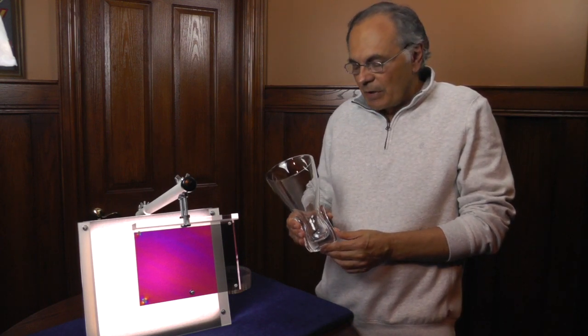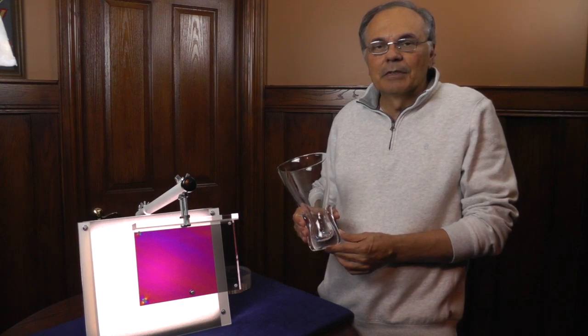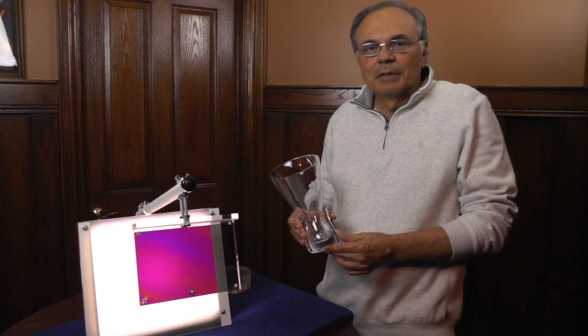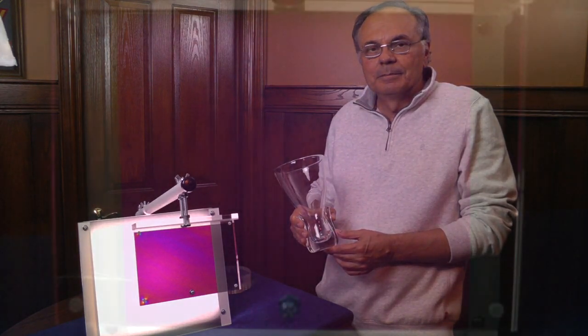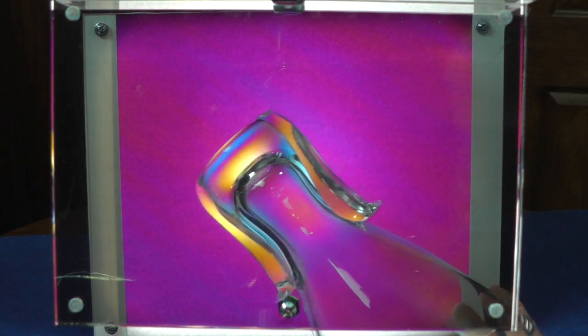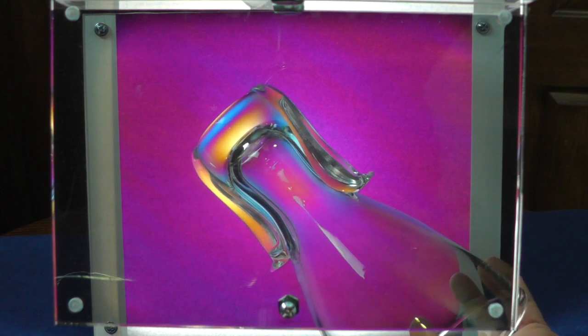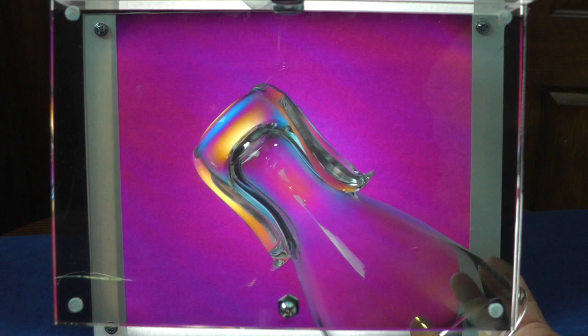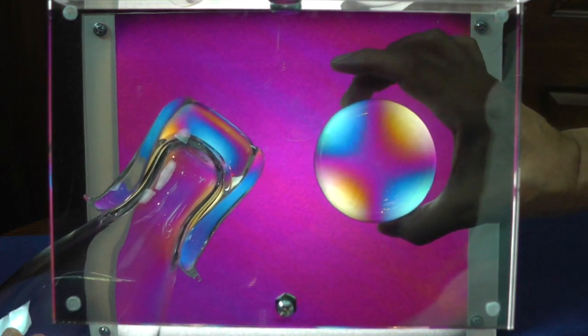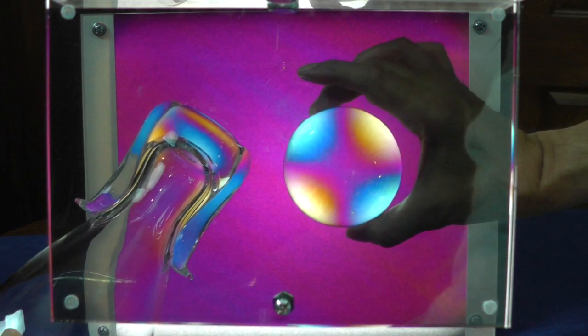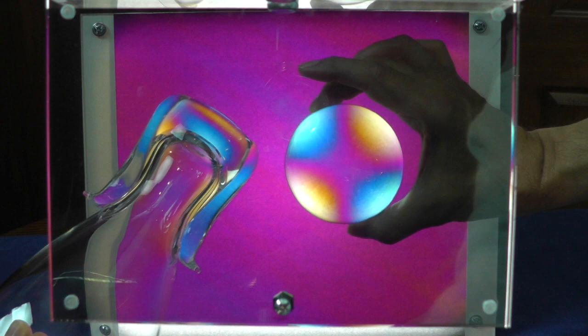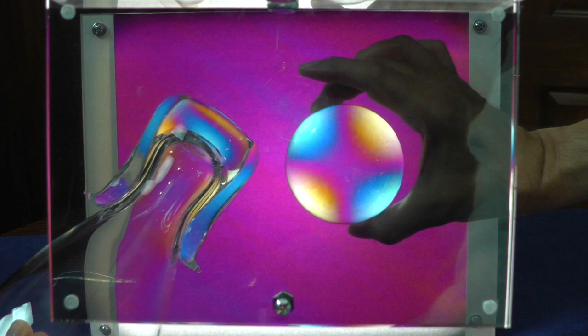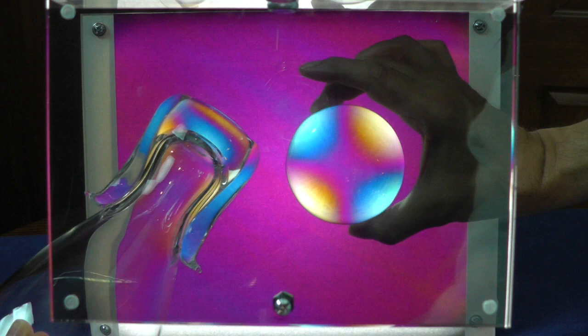This is a piece of Steuben glass. I was a technical consultant for Steuben glass in Corning, New York for about three years. I actually designed and built polishing equipment that they use to polish about 60% of their production. So let's take a look at what their piece looks like in the polariscope. You can see in this vase that there is a light strain in the glass. This is pretty typical of a vase that has a heavy section attached to a thinner section of glass. I used this gob to the side as kind of a benchmark. It's about an inch thick and about three inches in diameter. This is some glass that I bought over 40 years ago, so it has been stable for many years. It came from an optical company so I know that they're not going to send anything out that isn't right. So I've been using this as a benchmark. You can see that it has a gradual transition between the blue and the magenta and the yellow.